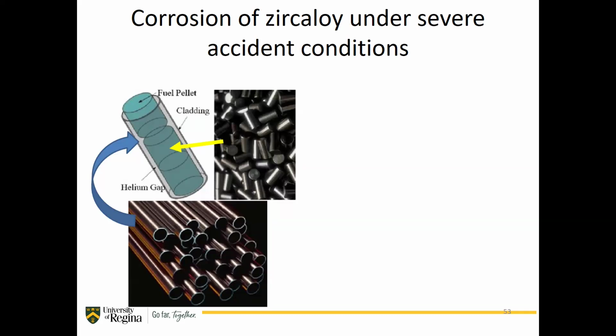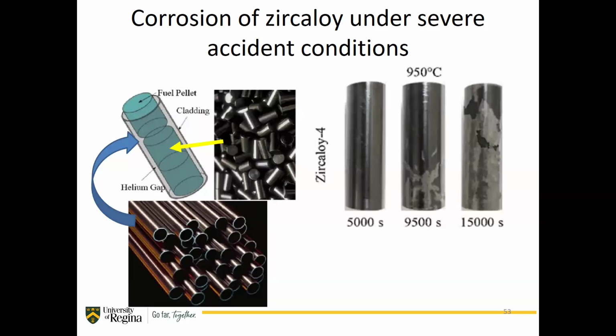So, corrosion of zircaloy under severe accident conditions. What actually happens to that sheathing, or cladding, or whatever you want to call it, of the actual fuel if you're under very high temperature steam? This is a really nice image, I think, showing this off, taken from a paper I had cited at the bottom, showing over time how quickly that zircaloy will corrode. And this is at relatively moderate temperatures. Like 950 is not nearly as hot as things in the reactor when temperature continues to increase.